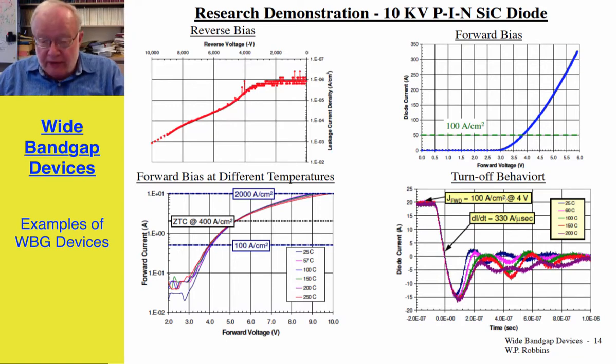Turn-off behavior is quite fast. Here we're going from 100 amps per square centimeter at a forward voltage of 4 volts with a dI/dt of 330 amps per microsecond, and it turns off starting from this point in something on the order of about 200 nanoseconds. And so we're talking about a fairly fast turn-off for this high voltage device. It's showing it at different temperatures, and it seems to be relatively independent of temperature.